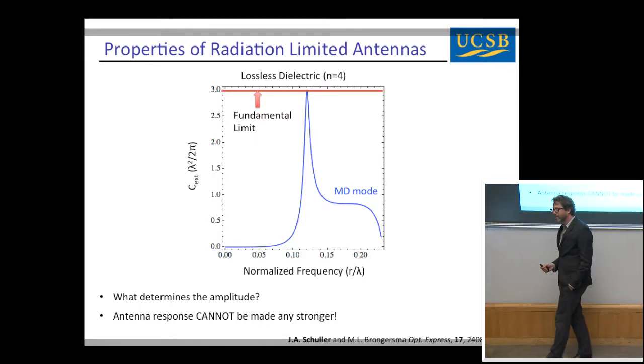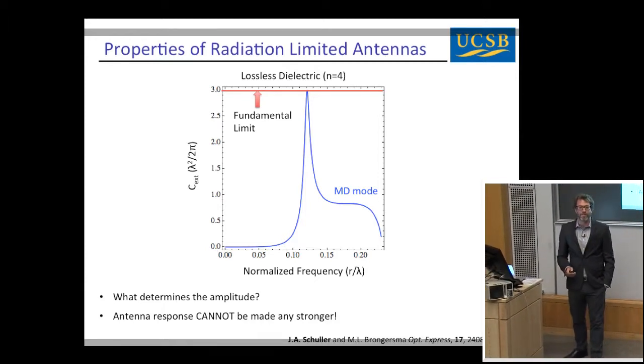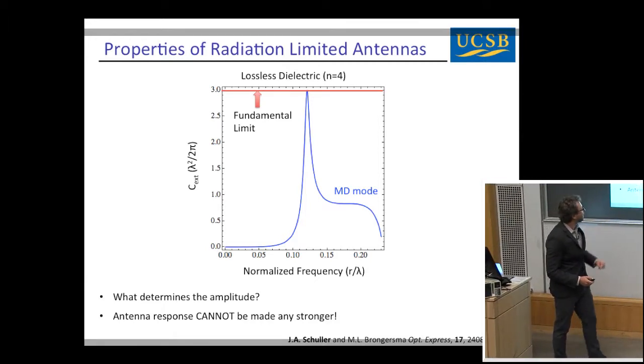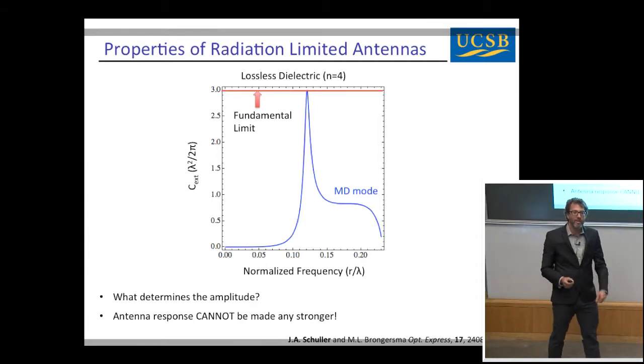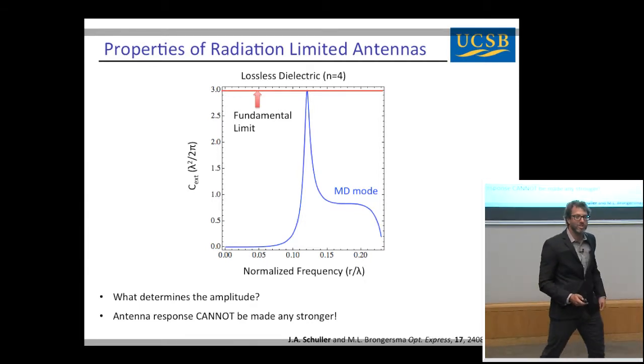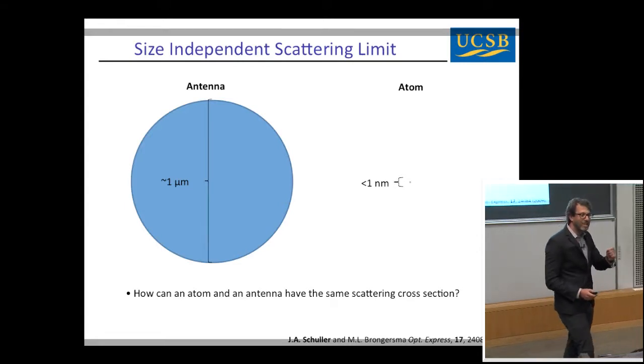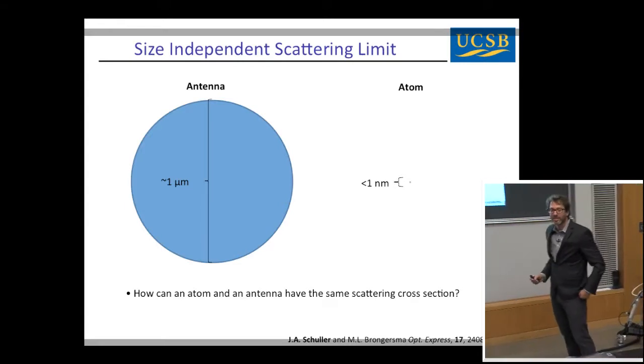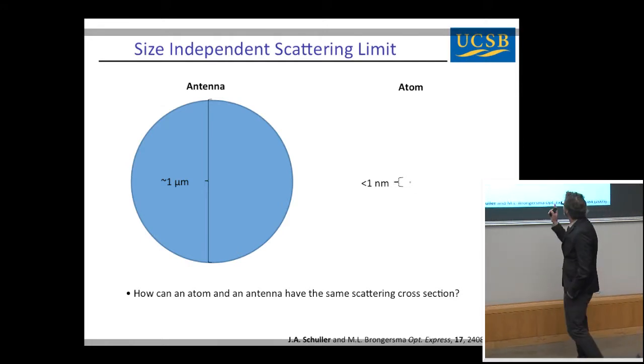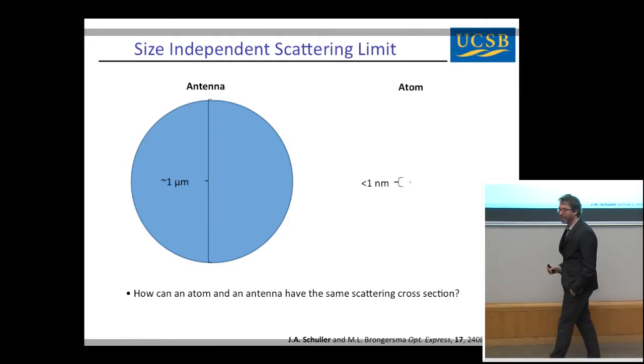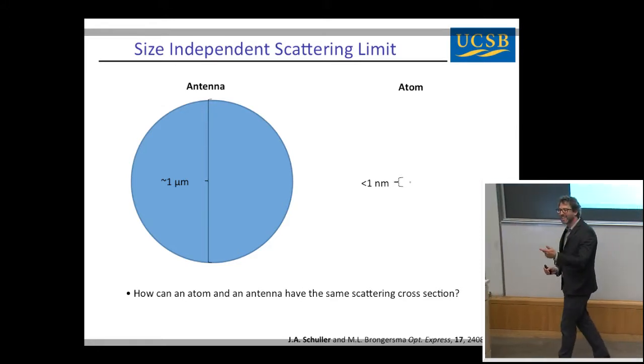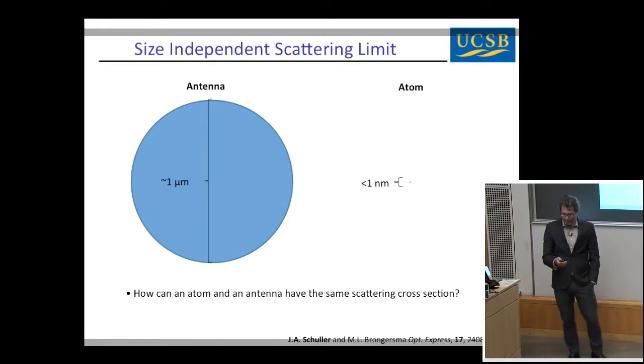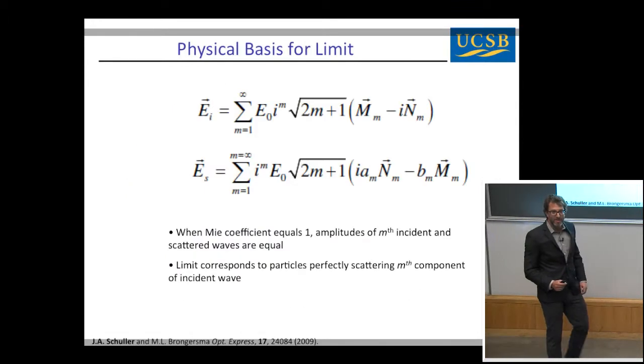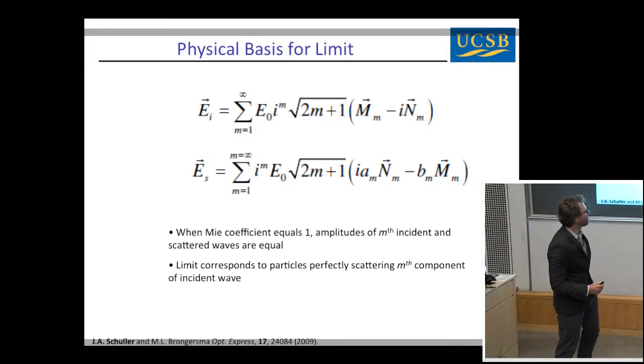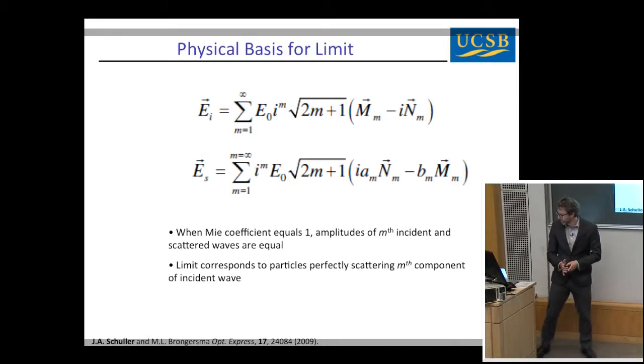Now this might seem odd at first, especially because when we look at what we've drawn here, nowhere in this limit does the size of the structure appear. So this limit applies equally well to a micron-scale antenna structure like we're seeing here, and to something three orders of magnitude smaller, like an atom. So how can these things have the same limit on their dipolar scattering or extinction spectra? Well, I know there's some math on the board, and probably I lost a couple of you already just by putting up equations, but it's really very simple.